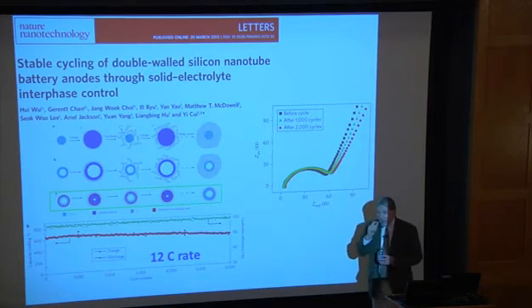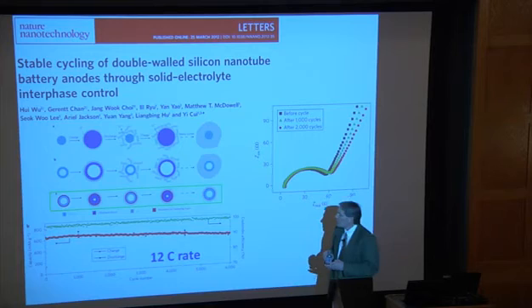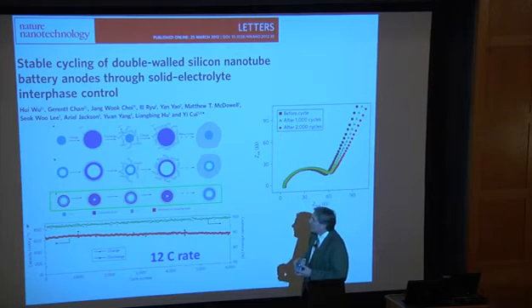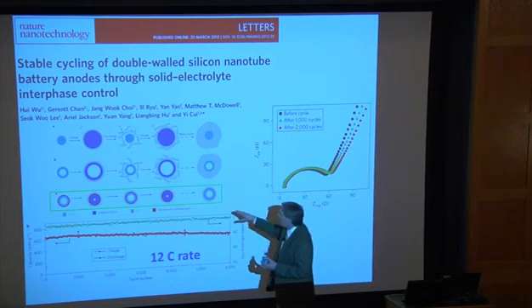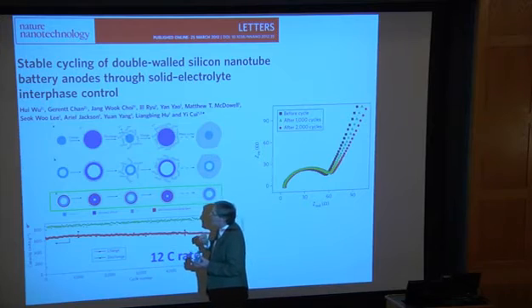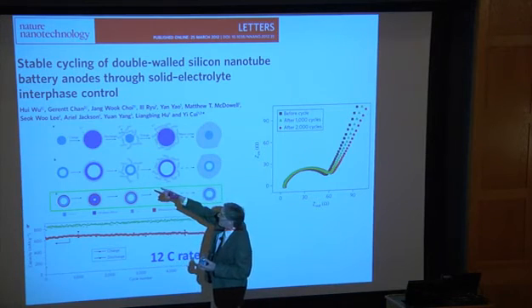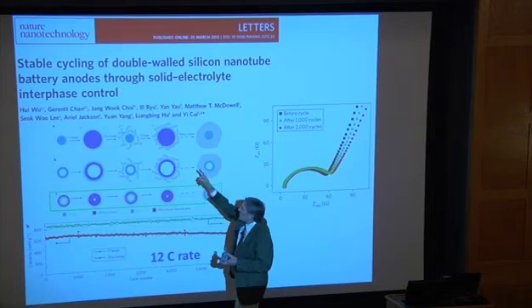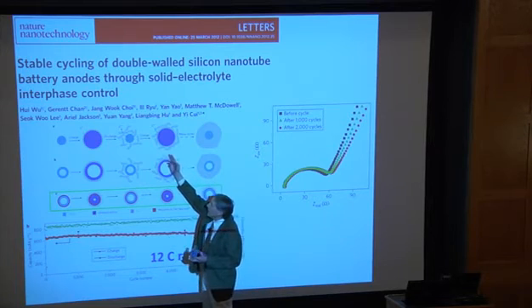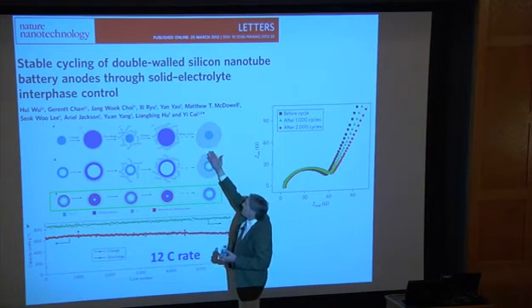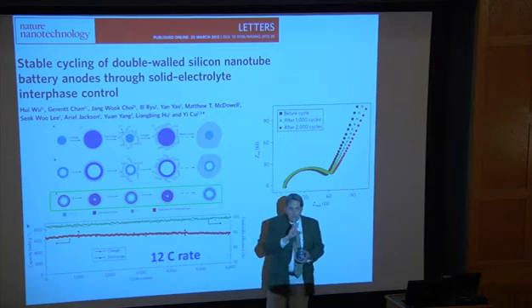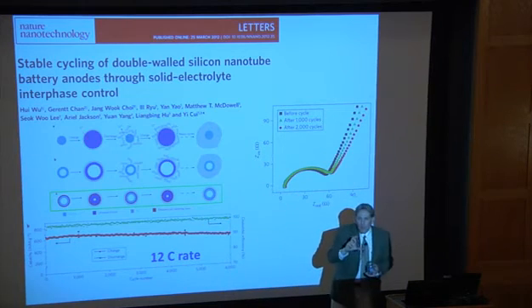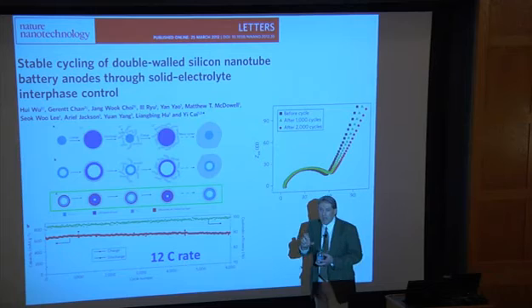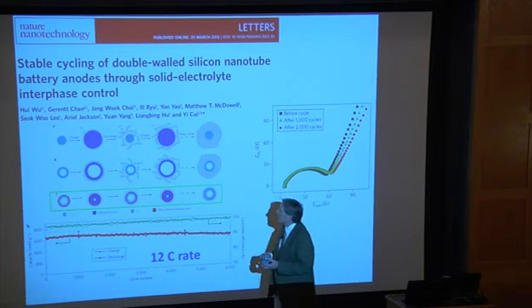There's a similar vein of work going on by Cui and co-workers out at Stanford. And in their case, the green box is the preferred system that they went to. The conventional system is shown on the top, where you just take pure silicon, you charge and discharge it, you keep getting this SEI growth. And this large gray region is this very thick SEI. When you get that thick, it's a bunch of lithium adducts and basically junk that forms on the surface.